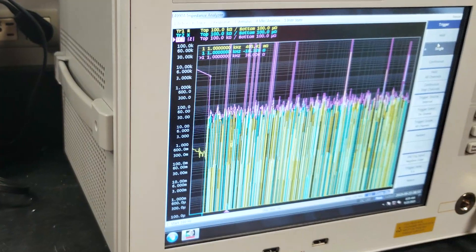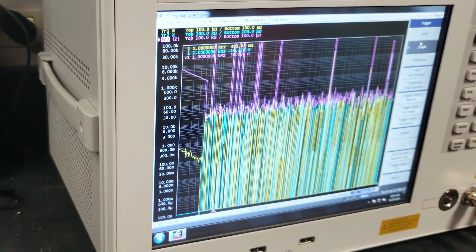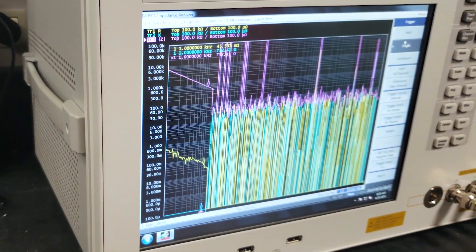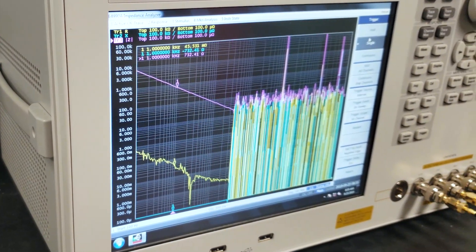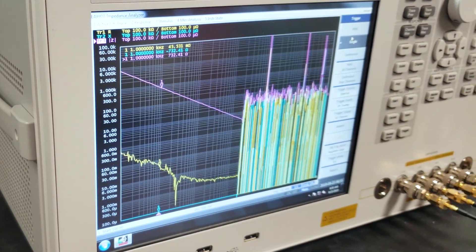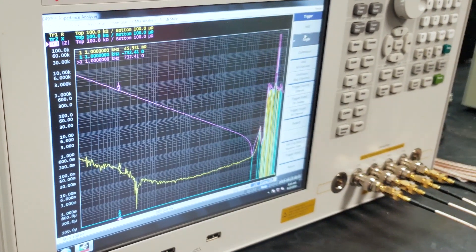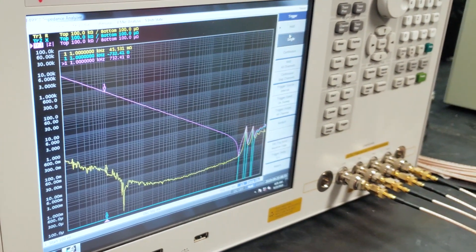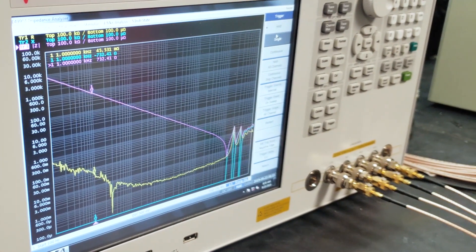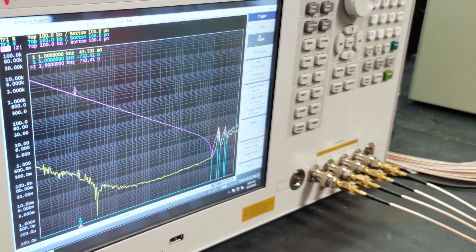When characterizing capacitors like KC-Link, its very low losses make it a big challenge for measuring ESR with precision and accuracy. Kemet utilizes state-of-the-art impedance analyzers with customized four-wire Kelvin fixtures to measure ESR levels in the low milli-ohm range with precision and accuracy. That's critical for optimizing designs.